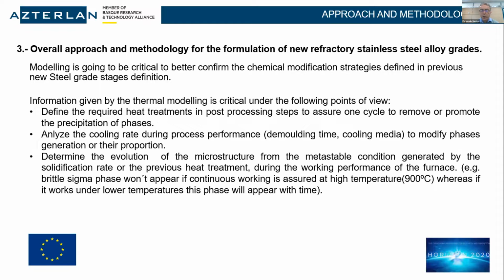Well, we can also analyze the cooling rate during process performance. We can decide if we want to demold more quickly or not, depending on the phases that we want to maintain in the final structure. And of course, we can determine the evolution of the microstructure from the metastable condition generated by the solidification rate of the previous heat treatment during the working performance of the furnace. For example, we have to consider that the microstructure can be modified at high temperature during the performance of the furnace, and this modeling can give us a lot of information about how it will evolve with the